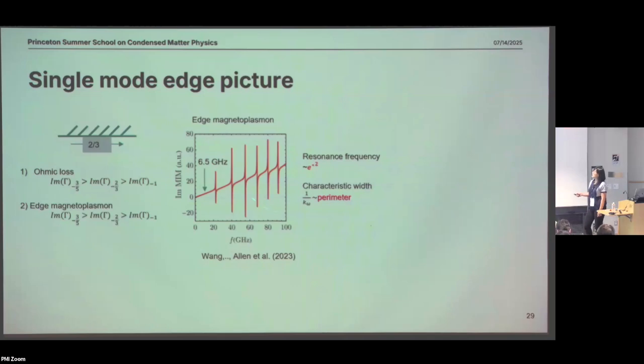That's one part of contribution. And there's also another part of contribution coming from the ohmic loss. So this material is not perfect, and the mobility is also not very high. So there is a huge contribution coming from sigma XX, the residual conductivity. So the ohmic loss part and the edge magnetoplasmon part would form the major contribution of the edge signal that we saw. And then we can provide theoretical predictions of what type of signal magnitude we can see for each of those states.